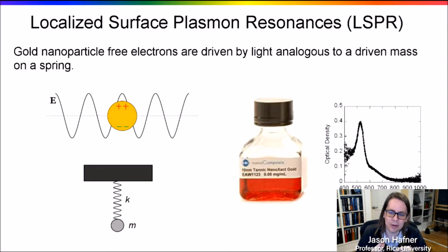So it's basically the light, which is an oscillating electric field, drives the charge to move up and down in a sinusoidal pattern in time. So it's just shaking the electrons, is all it's doing. But if you think about it, if the electrons try to leave the gold, they're going to be pulled back, because even though the light is pushing them up, if you leave a positively charged nuclei and try to leave, it's going to suck the electrons back. So they're being driven out, but there's a restoring force pulling them back in. So ultimately, it's like a mass on a spring. The electrons are just oscillating up and down. It's like a driven mass on a spring even.